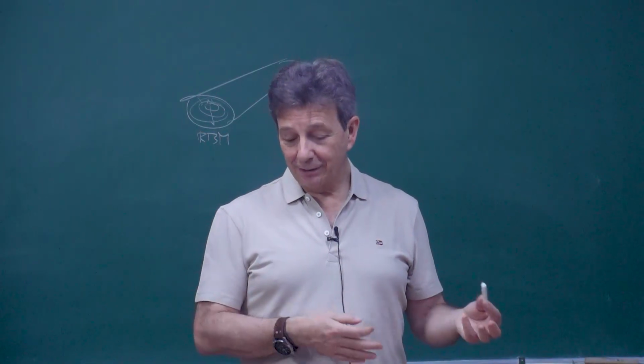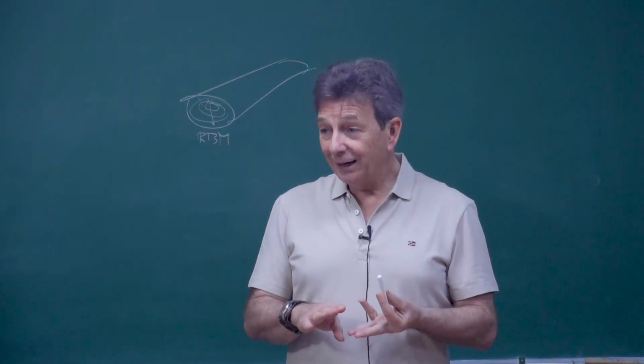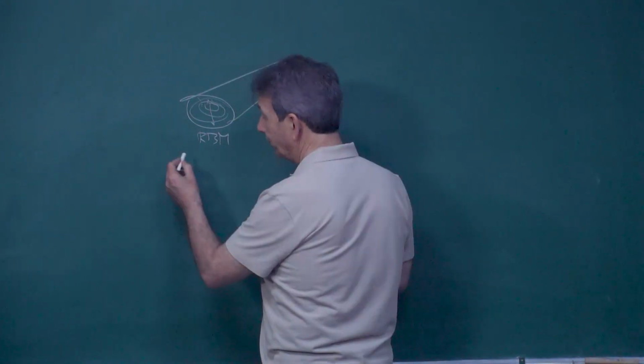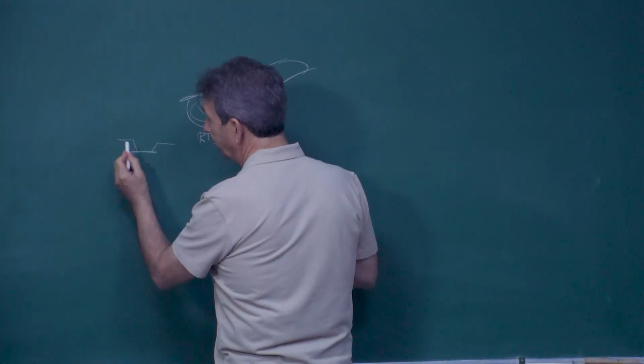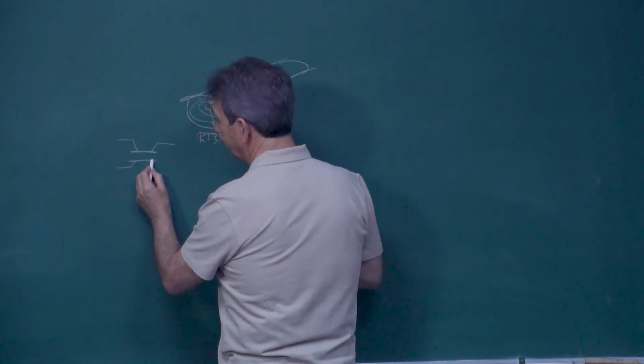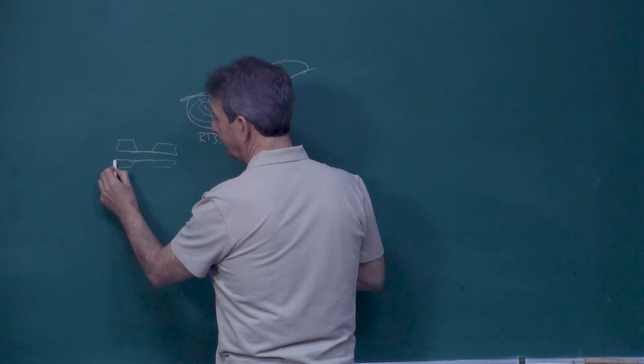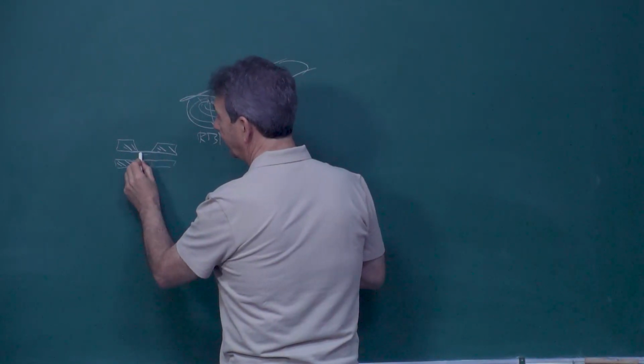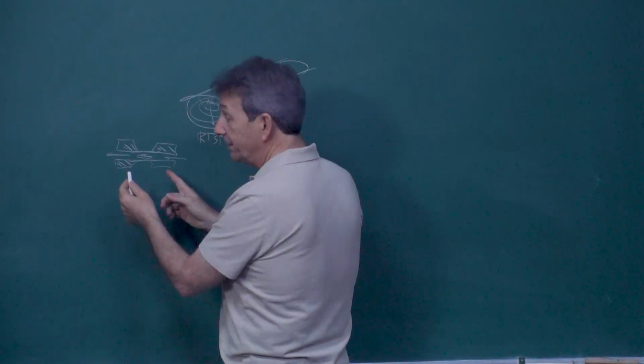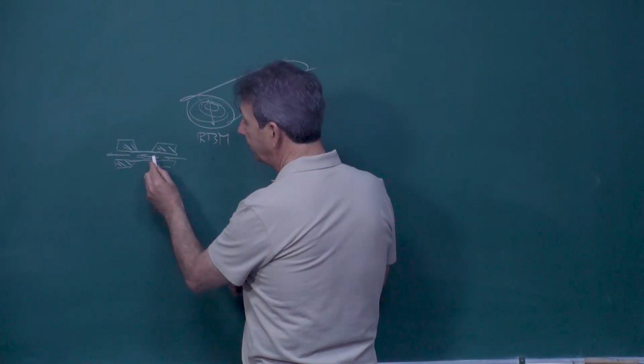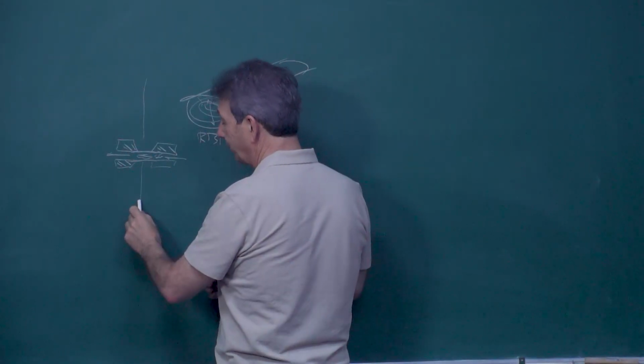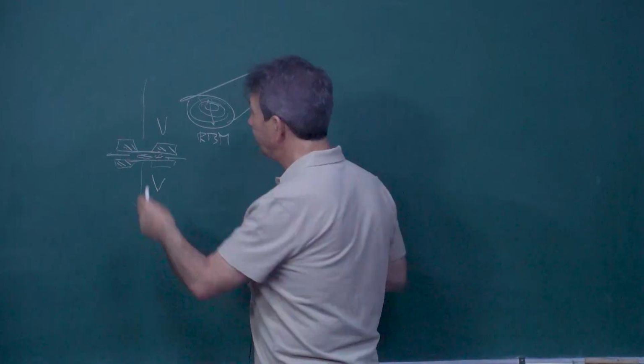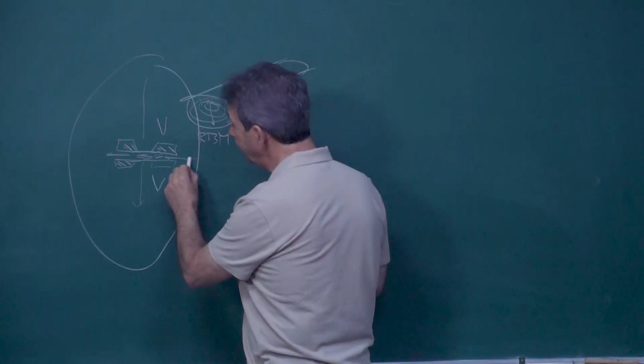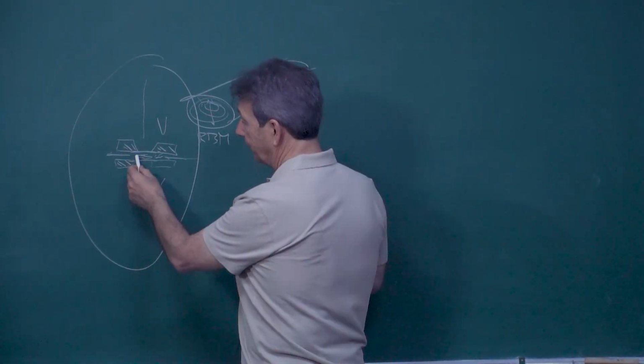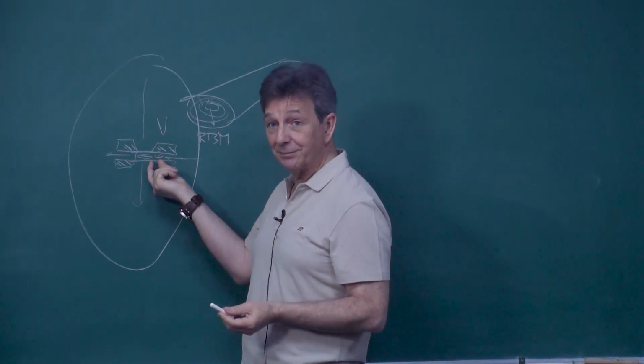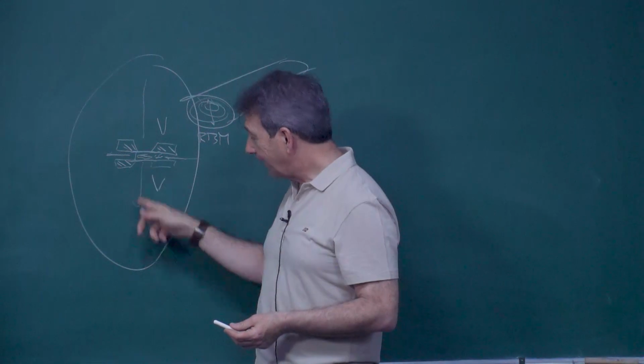So if you're looking at the catalyst, like we saw yesterday, these transmission electron microscopy reactors, well, this reactor is very, very small. It's smaller than my finger. So you get like a metallic system with a window that could be a graphene window or whatever, something like that. So you get a metallic piece here. Over here you have your sample, the flow going through, but this is very small. This is like a few millimeters, and over here you will have liquid, or you will have gases, but then you have all the electron beam for the microscopy here, and everything here is vacuum. So the whole chamber is very big and everything is vacuum, and you only get a little bit here, and you are dealing with a few microns here, and the whole system is only a few millimeters, but the reactive area is small, and this is good enough for the electrons to go through and reach the detector.